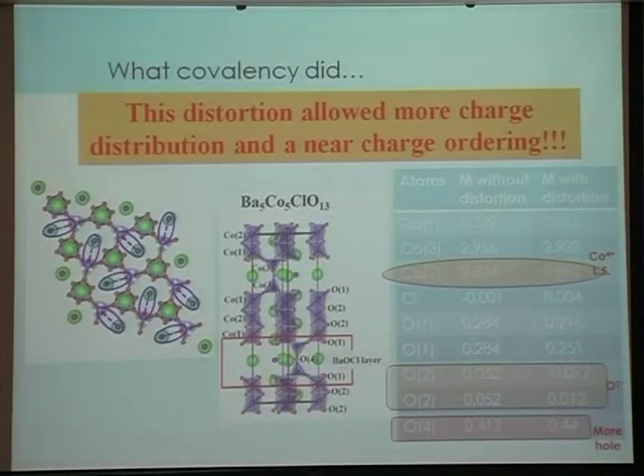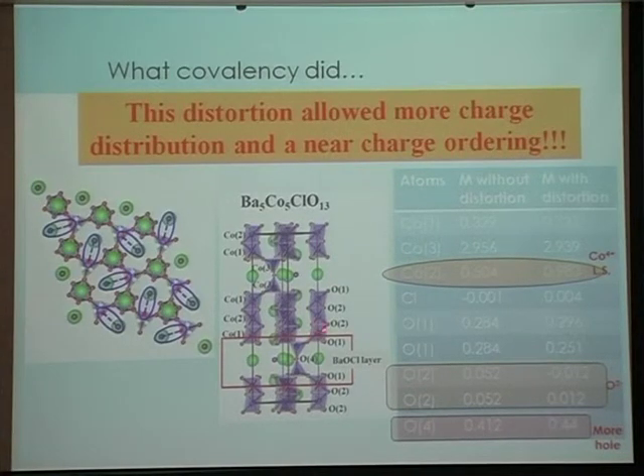And then, having these particular distortions in, if the calculations are repeated, I'll not go into the detail of it, what we find is that this particular oxygen takes up even more hole. That means by going towards the chlorine, this oxygen is ready to take up more hole. So it's stabilizing by going towards the oxygen, making a chlorine-oxygen pair, smaller dipoles all in the plane, but randomly directed.